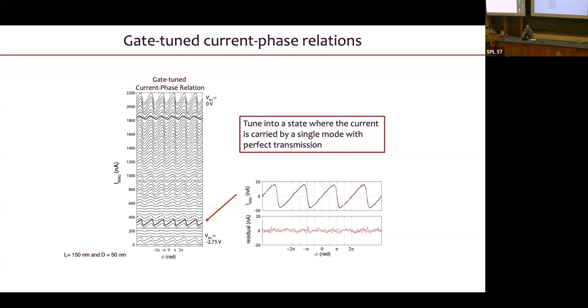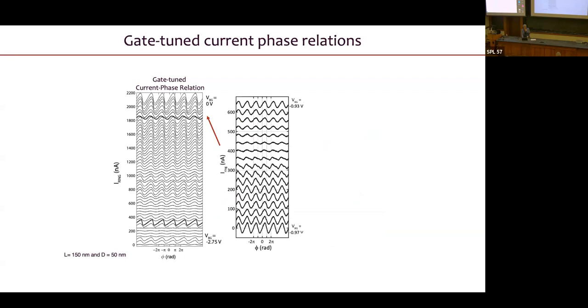I did not expect to see such a skewed current phase relation. There are other current phase relation papers in the literature where it's just barely visibly skewed from a sine wave. In here, it's actually really consistent with perfect transmission. We also see these backwards things, and here I'm just going to zoom in on this backward skewed current phase relation.